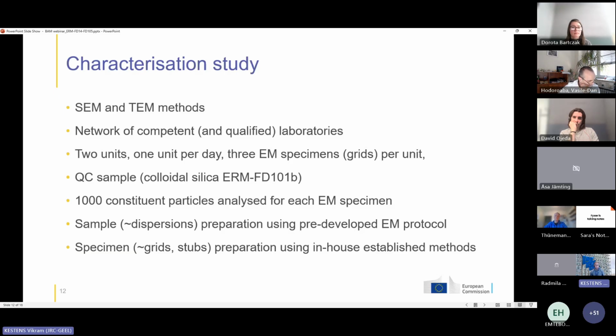So the laboratories had to measure 1,000 constituent particles. Here, I can mention that for some laboratories that went quite straightforward, because they could analyze the particles in a semi or fully automated manner. But there were also laboratories who had to do the counting manually, and measuring 1,000 constituent particles per grid or per stub is quite time consuming. So we also saw some differences there.